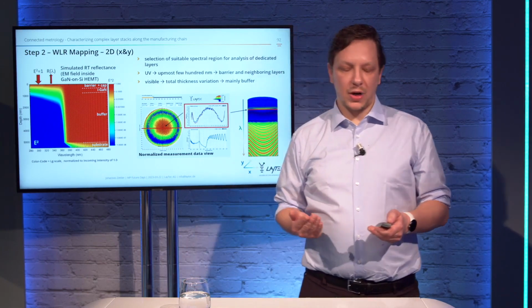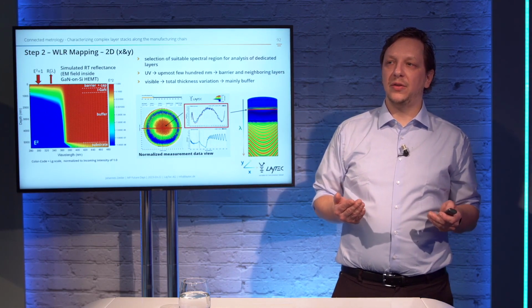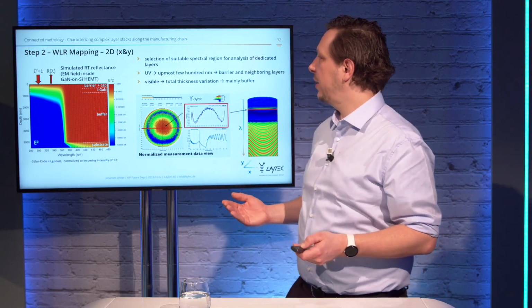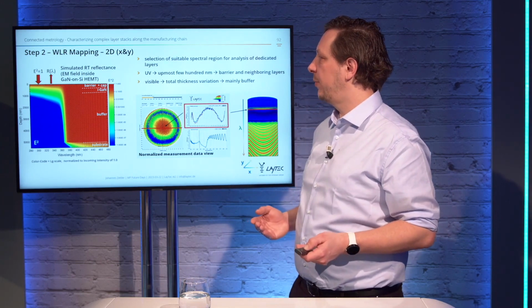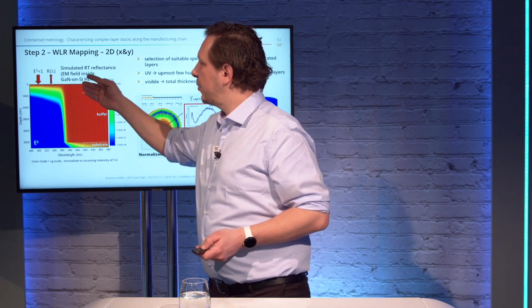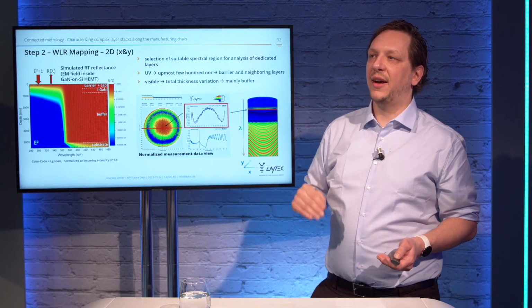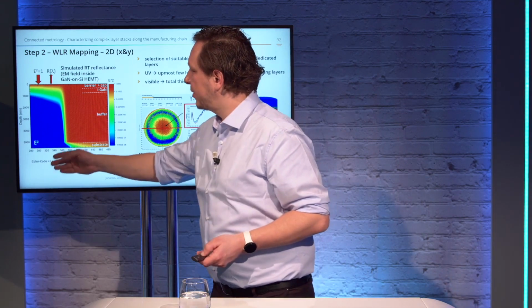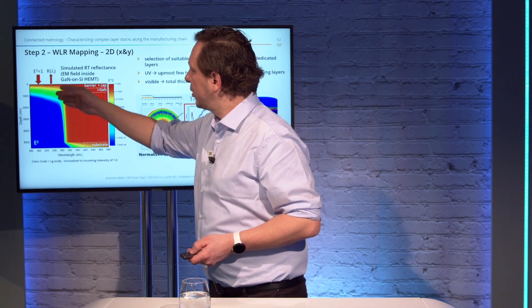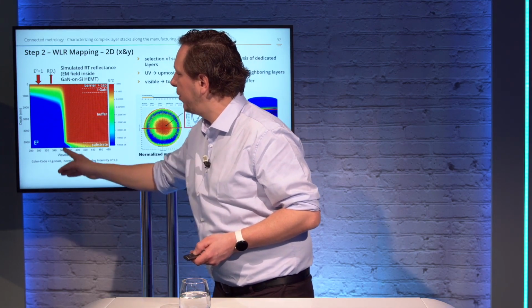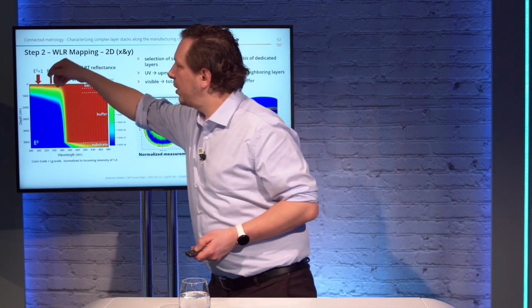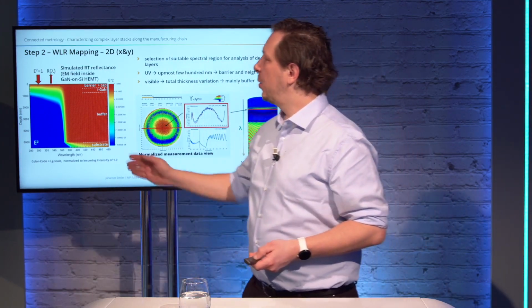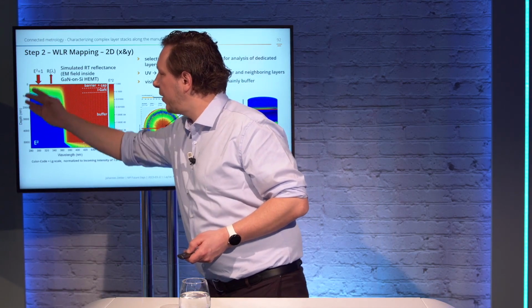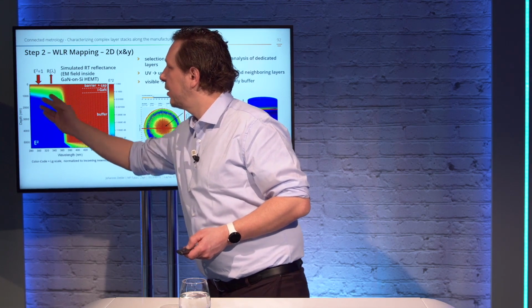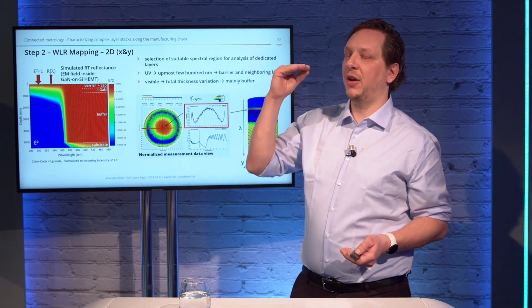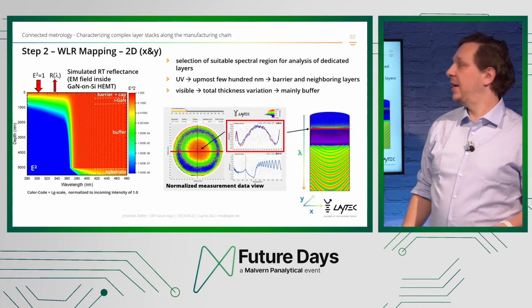So first of all, let's look at the structure, and we need to see what we are actually measuring. For that, we simulated the reflectance of the typical HEMT structure we've seen before. And along with the reflectance, we can also simulate the electric field inside the stack. You see here, this is a log scale, so in this region below the gallium nitride band gap, the light does not really penetrate much into the stack. And all our reflectance signals in the wavelength region up to roughly 360 nanometers are defined by the upmost layers, which are the critical layers in the HEMT stack.